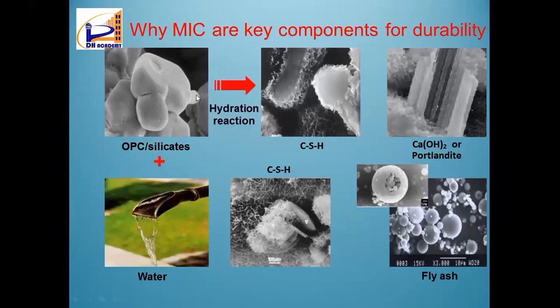Water will react with OPC. That process, we all know, is called hydration. The products are hydrated calcium silicates, which contribute to strength, and calcium hydroxide or portlandite, which is weak in concrete because of its crystalline structure. This calcium hydroxide, over a period of time, if it comes out, that is called leaching of lime. If leaching of lime happens from concrete, that means concrete became porous, so moisture will go in and attack the reinforcement. And once that corrosion happens, the reinforcement may expand 1 to 6 times.